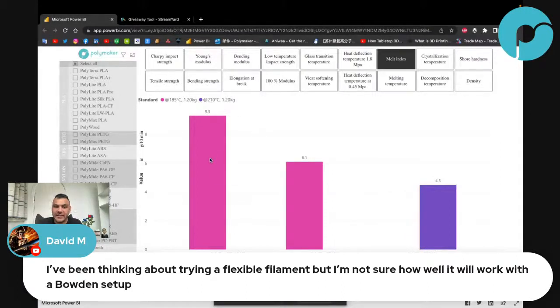And TPU 95 HF, the high flow version, is 9.3. So it means 9.3 grams, and it's at 180 degrees. Why? Because if we put 210 degrees, the amount is too high. It's above 15 grams, and above 15 grams is considered not good for this testing method. So now you can see the advantage of using HF, because you won't require as much pressure.